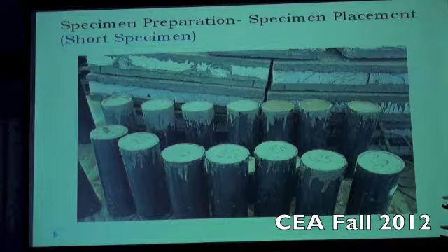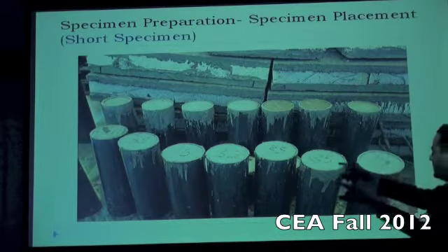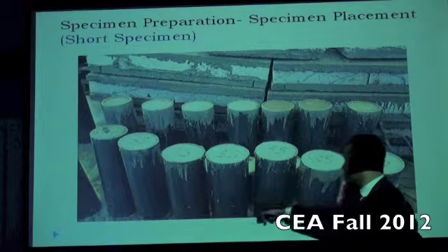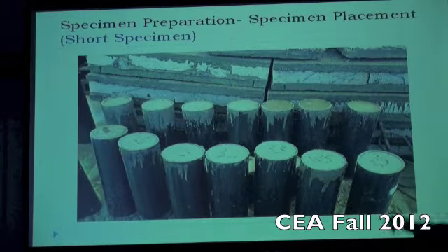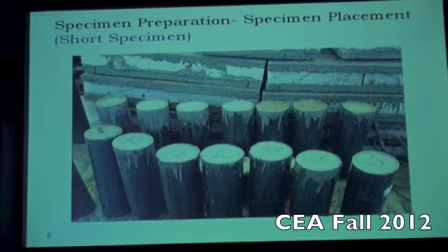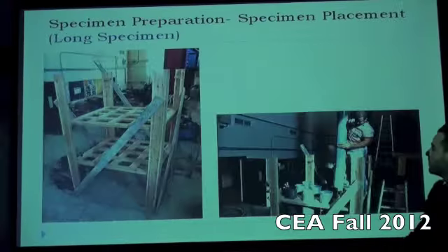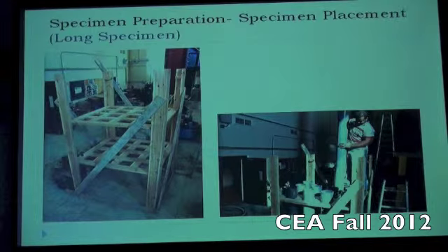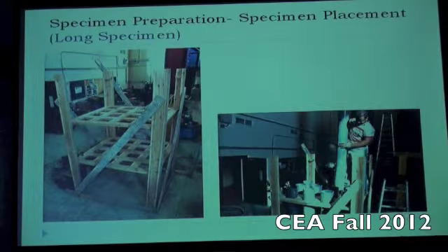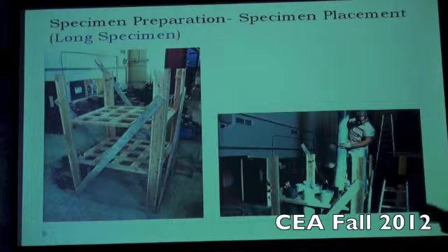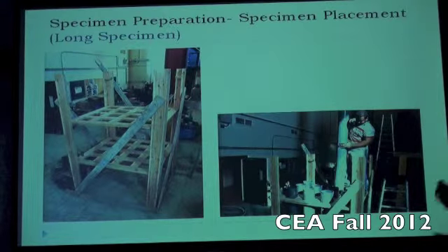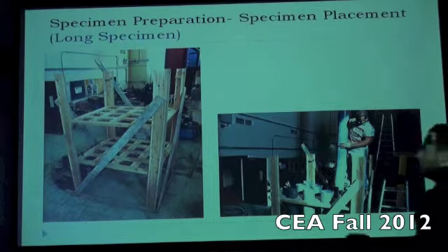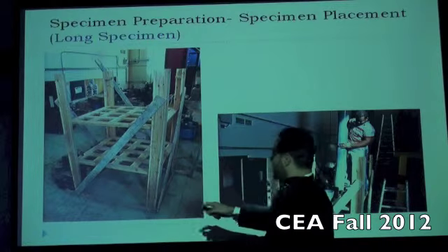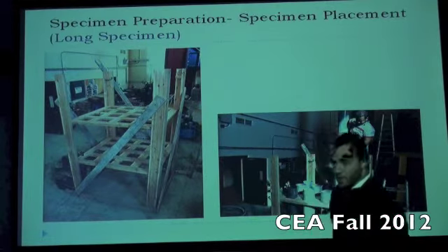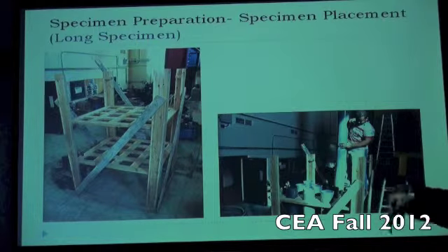For the short columns, 60 centimeters as you can see, and in between about 30 centimeters, we don't have a problem. We just put it on the floor and cast it. But for the 240 and 300 centimeter ones, it's very high and very difficult to cast, standing on the floor alone. So we made a wooden frame with 16 openings, just the diameter of the pipe. And as you can see here, we put the pipes inside.